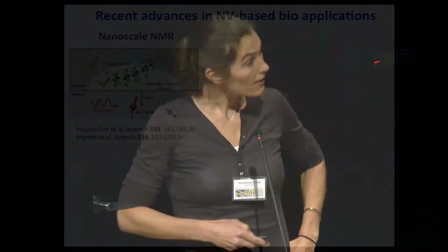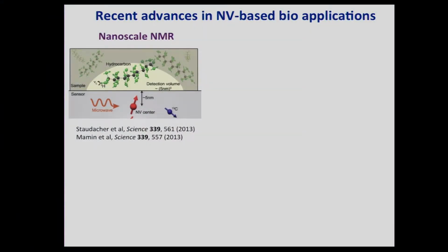Okay, so though neural imaging has not been experimentally demonstrated, there have been a few beautiful experiments recently that have really shown the power of the NV center as applied to what I call wet and squishy systems. I'm trained as a hard condensed matter physicist; there's a divide in condensed matter physics between hard and soft. In this particular case, 2 experiments came out around the same time in which 2 groups detected an NMR signal from a very small volume, about a 5 nanometer cube of nuclear spins, in just a thin film of oil.